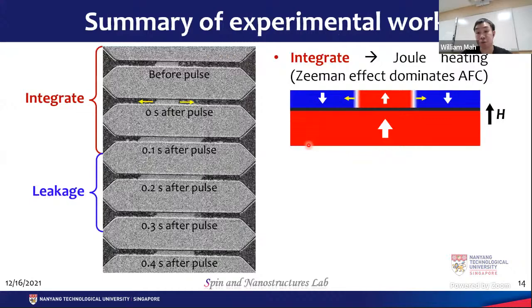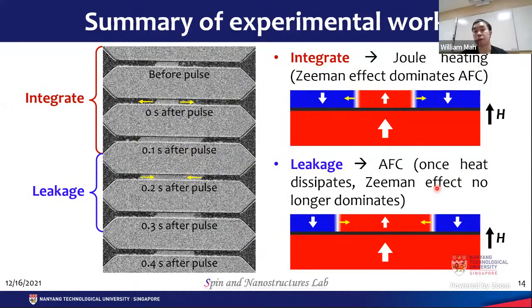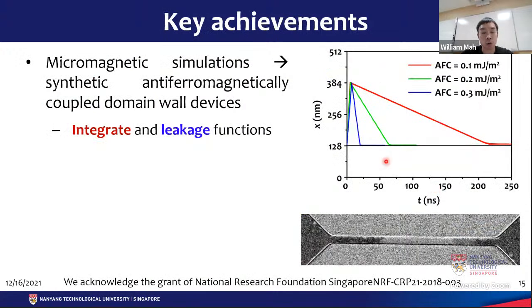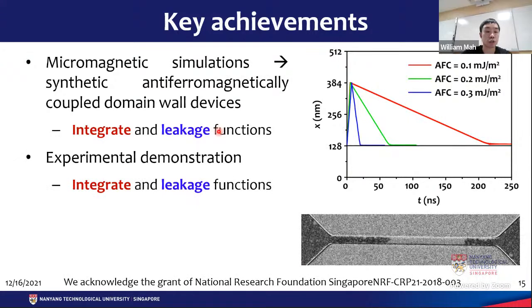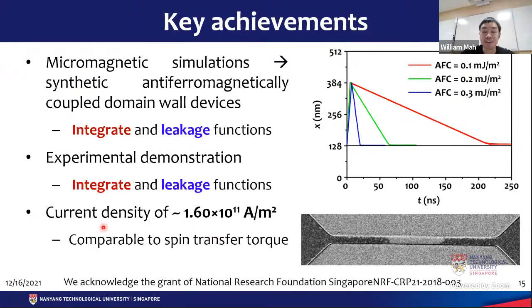That is what gives us our integrate function. And after some time, as the heat dissipates, the Zeeman effect no longer dominates, and the domain walls come back by themselves. That is the leakage function. All in all, in the simulations, we have demonstrated integrate and leakage functions, and so do the experiments. Even though the integrate function is achieved by Joule heating, the current density is comparable to spin transfer torque. So this synthetic antiferromagnetic design is a potential candidate as an artificial neuron for neuromorphic computing. Thank you for your time.